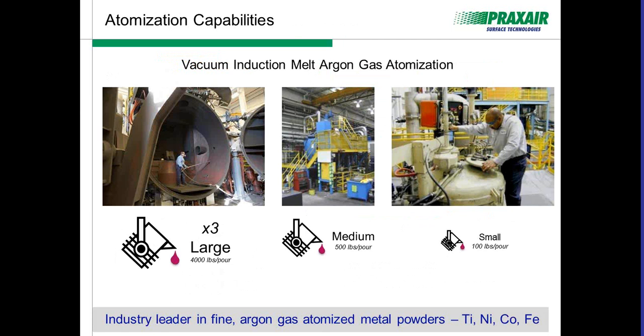All of these atomizers operate in full vacuum, so we pull a full vacuum on them to get rid of all the air and other contaminants inside, and then backfill with a high purity gas. Using high purity gas is key to maintaining the highest quality of powders. It reduces slag, so you can control your chemistry much more closely than melting in air. It also prevents oxidation during the atomization process. We use this technology for titanium-based, nickel-based, cobalt-based, and iron-based powders every day in this plant.